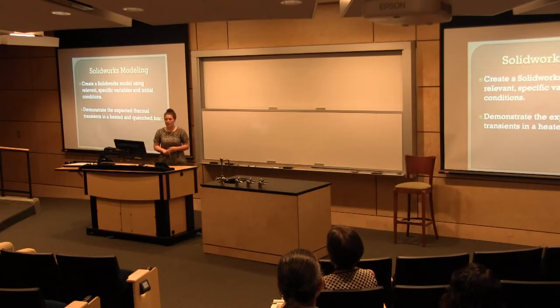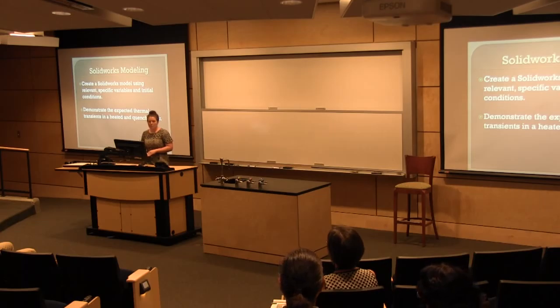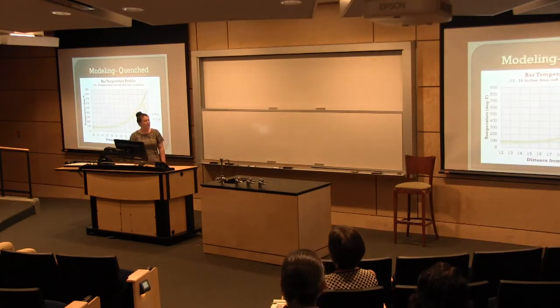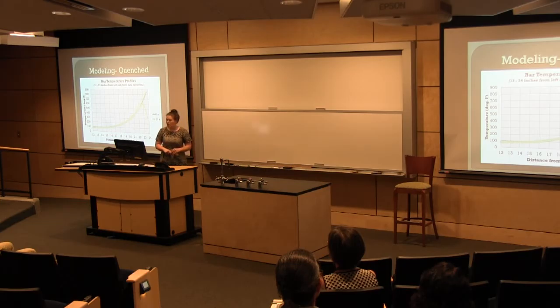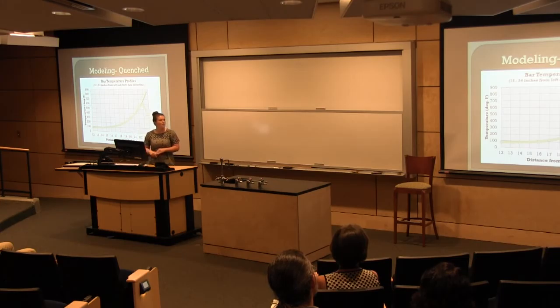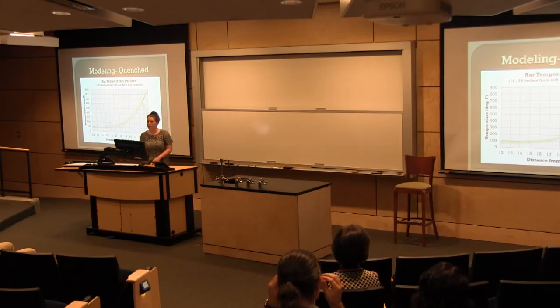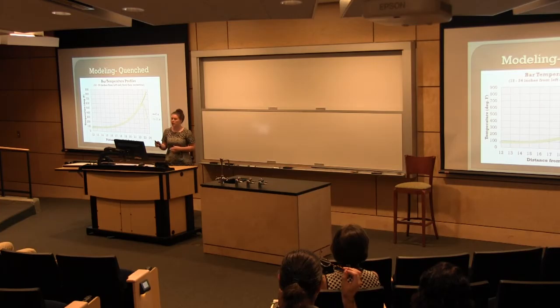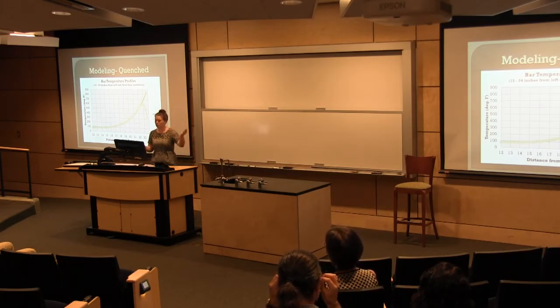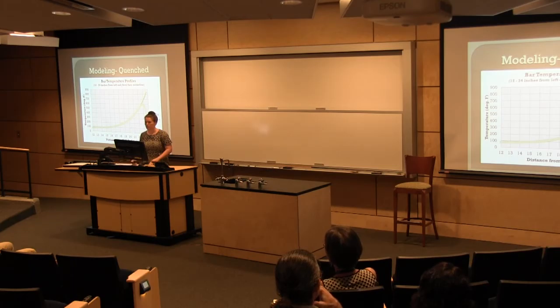So as far as SolidWorks modeling, we wanted to create a model with relevant specific variables that would actually demonstrate the heated and quenched bar. So this is actually a model that Dr. Bailey gratefully made for us, and you can see the 0-second plot, the darker green line here, is the initial thermal plot of the bar, and then the lighter green is actually after the quench condition. So you'll see that the heat does transfer to the rest of the bar, which is going towards the left, and to the right, which is into the water.